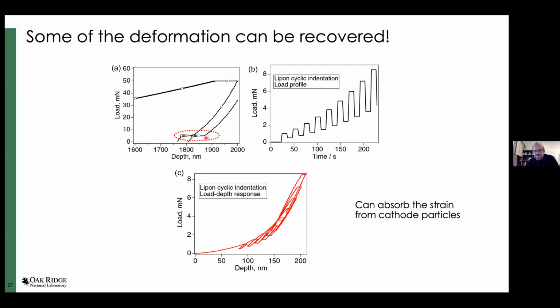So it can densify and then restore that free volume a little bit. Now, this is not new for many glasses. Many glasses can do that, but you will need to input some thermal energy into the material to allow it to restore this deformation. In LIPON, this happens at room temperature, which is absolutely bizarre, and which inspired us to do this weird test where you apply the sawtooth signal to the nano-indenter.